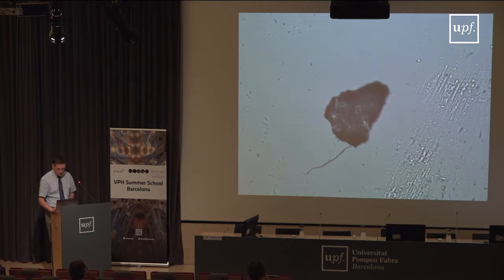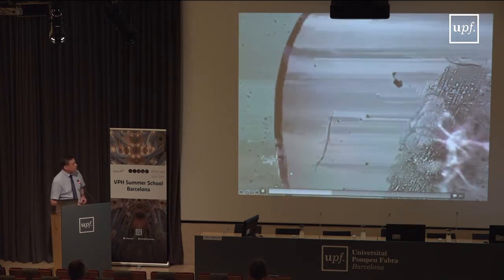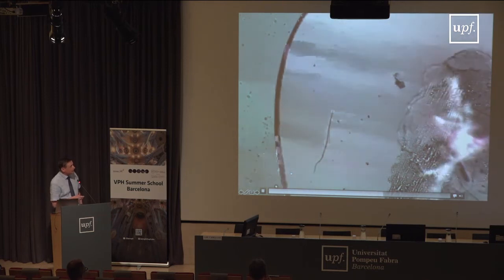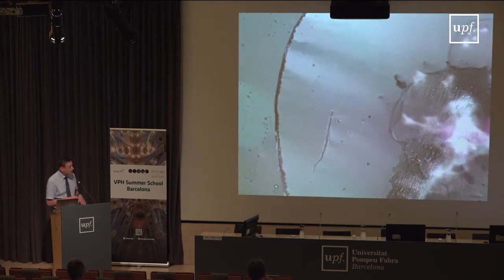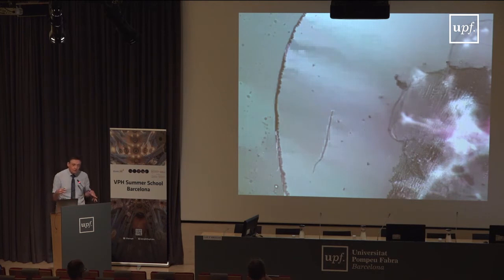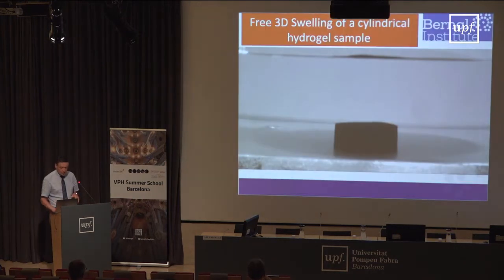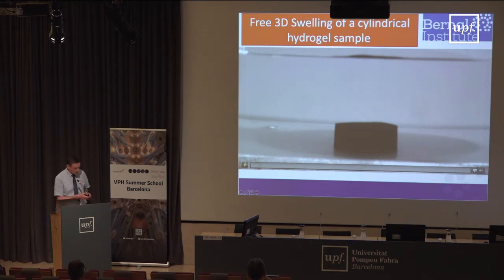That's it. It's almost running away, but you can see very clearly that it has what is called the cauliflower effect. It swells one side and then the other side, so it's a very non-homogeneous swelling of the phenomenon. So you see surface instabilities coming up. And to illustrate this even a little bit better, I can show you another video which we've been making of